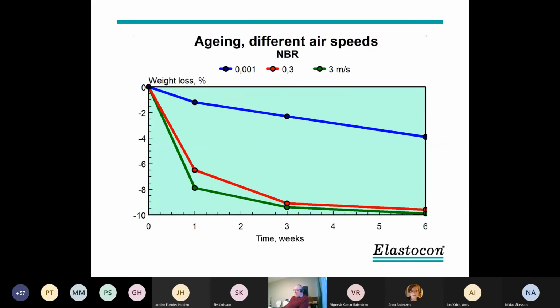What we did then to examine the air speed influence: we designed ovens with a laminar air speed of 0.3 and 3 meters per second. The blue line is our cell ovens, or our cabinet ovens, where the air speed is only dependent on the air exchange rate. That means it's in the range of 0.001 meters per second. So we can see that the higher the air speed, the more we lose in weight. In this project, we tested 4 compounds. We also tested tensile strength and a lot of other properties. But it's easy to show what happens when you look at the weight loss.